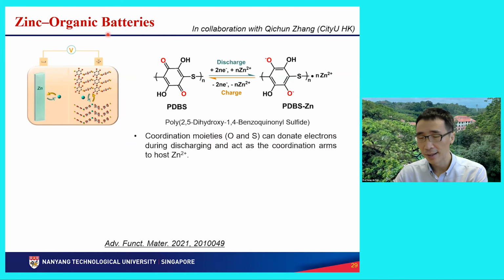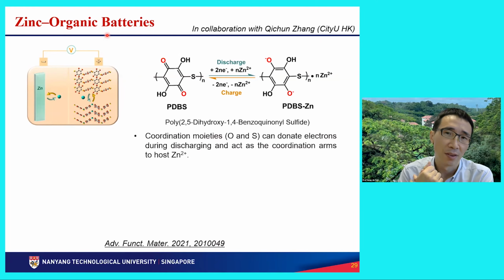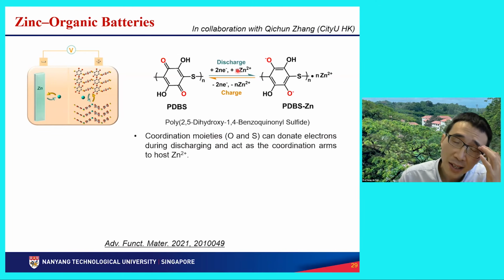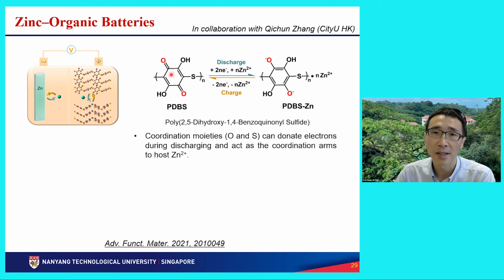But what about replacing it with organic? Some of the organic materials can also be very stable in aqueous solution, as long as the molecules are designed and engineered in a way that they are stable. So in this work, in collaboration with Professor Qichun Zhang, previously in MSE of NTU, now in City University of Hong Kong, they designed this kind of molecule, PDBs, containing oxygen and sulfur moieties, which can be electron donors during the discharge process. So if this molecule can donate electrons, and the electrons can be captured by zinc ions, then they can have a redox reaction. So this electron donating, the charge transfer reaction, if it's reversible, then this material can be used for batteries.